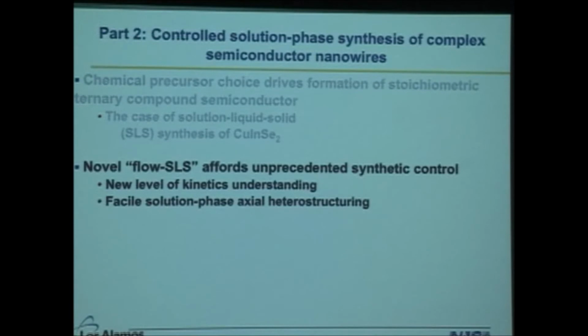Okay, and last but not least, newer work in my lab. We are trying to make SLS better by making it more controlled. As I mentioned, traditional SLS is one pot growth. Similar to quantum dot growth, you heat up a flask of solvent. Some of it's coordinating, some of it's non-coordinating solvent. You, in this case, add a slurry of nanoparticles, often bismuth or tin, something low melting. They suspend and are molten, and then you inject your precursors, and then particle growth happens typically very, very rapidly in not a terribly controlled fashion.